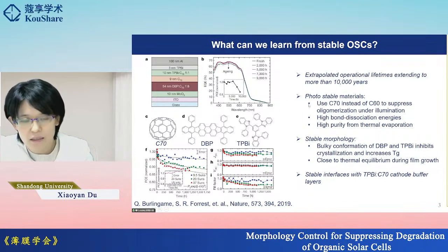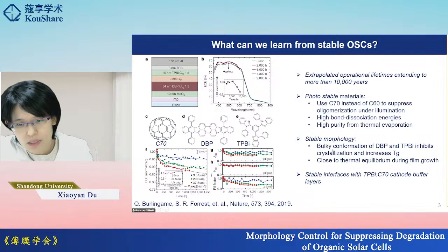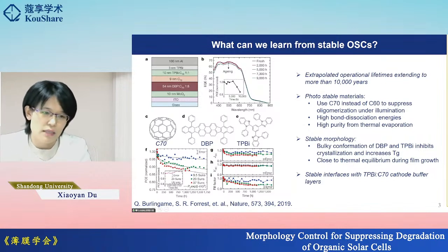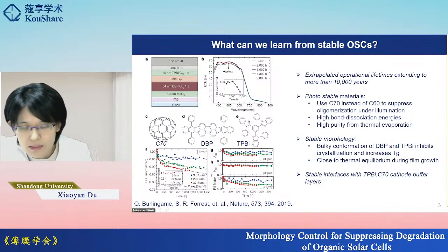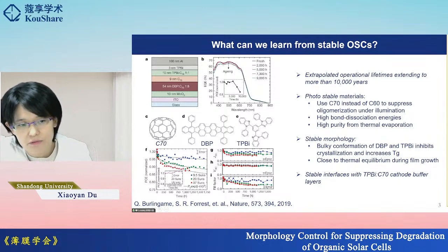We can divide these aspects into three: the photostable materials, the morphology, and the interfaces. About the stable materials, the authors commented that C70 is used instead of C60 because this can suppress the photo-induced oligomerization. And these materials have very high bond dissociation energies. Also, due to the evaporation, the materials are purified, so they have very high purity in the active layer.